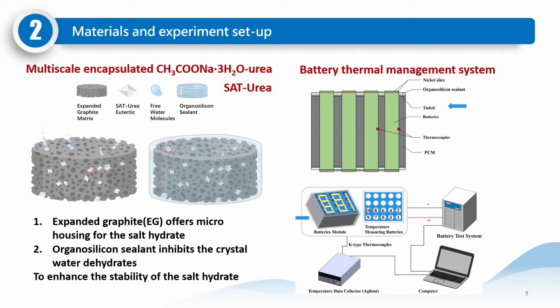And in this study, we prepared a multi-scale encapsulated sodium acetate trihydrate urea. We call it SAT urea. We use an expanded graphite matrix to absorb the SAT urea eutectic into the micro pores inside it. It's a micro scale encapsulation strategy, and on the surface we also use an organosilicon sealant